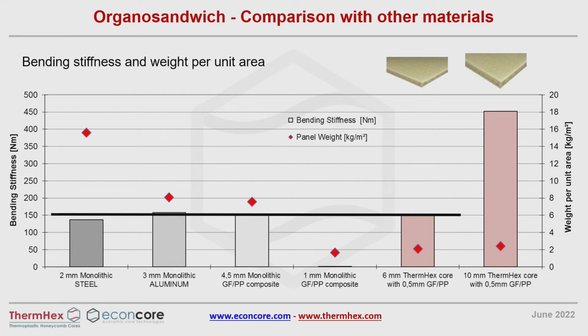And if you then look in the fourth position, we have the two skins, just 2 times half a millimeter glass fiber, which is about 2 kilogram, but of course very little bending stiffness with such a low thickness. But if you put these 2 times half a millimeter onto a sandwich core of 5 millimeter, then you get a 6 millimeter thick panel, which has then a weight of about 2 kilogram and has about the same bending stiffness than the other materials.